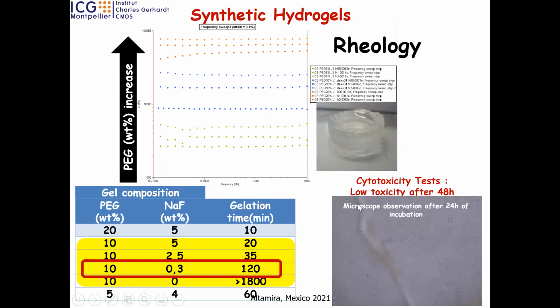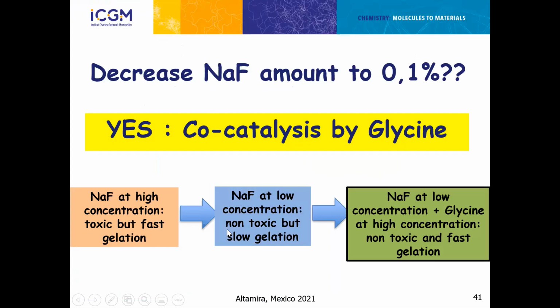The problem was, okay, there is no cytotoxicity for the cells after 24 hours, even after 48 hours, but after 3 days, all your cells are dead on the surfaces. We explain that by the F-. F- is cytotoxic for cells at this concentration. So the idea is to find a way to decrease this concentration of F-. The idea is to work at about 0.1%. At this concentration, we are biocompatible.